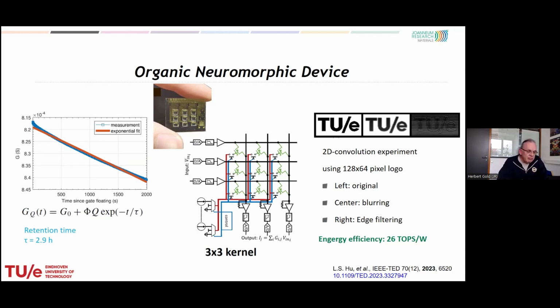And this was applied to the convolution experiment, and there they used a 128 times 64 pixel representation of their logo, and you see on the left the original, and then they programmed the kernel for a blurring filter, which worked, as you can see in the center of these 3 logos, and also the edge filtering worked, as you see in this darkened picture on the right. Also, they extracted an energy efficiency of 26 tera operations per second per watt, which is considered as an excellent efficiency.